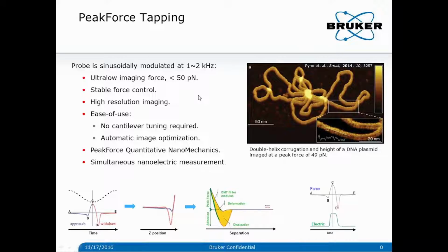The way to examine mechanical properties with AFM is through so-called force distance curves. Because of this, we use the PeakForce Tapping technique. PeakForce imaging is based on real-time force capture of the force curves. PeakForce Tapping uses a sinusoidally modulated probe at off-resonance, low frequency. So it doesn't rely on mechanical resonance, but it is a tapping mode. And the tapping frequency is typically 1 to 2 kilohertz for this study.